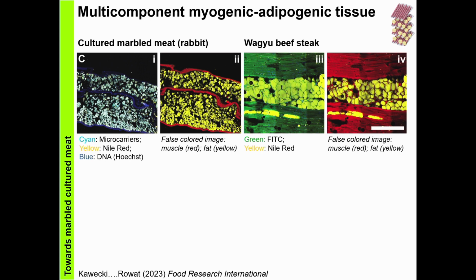So what does it really look like? Well, Stephanie showed also these beautiful cross-sections yesterday that she generated, showing, in this case, rabbit marbled meat, in contrast with the Wagyu beefsteak cross-section. And again, you can see, as she mentioned, that the length scale needs to still be tuned. The muscle here is shown false colored in red, the fat component in yellow, but we are getting relatively similar length scales, at least for the fat, and this process can easily be tuned.